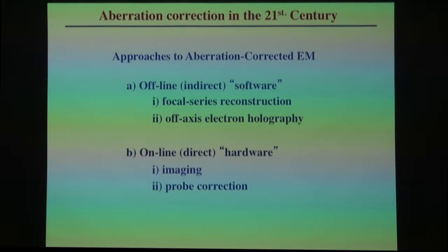because people are a bit worried about what high voltage microscopes do to a sample. You're going to cause radiation damage. These 1 million volt microscopes are very expensive. So maybe if we can overcome spherical aberration, then we can achieve better than 1 angstrom resolution at a lower voltage. Now, it turns out there are several different ways to correct aberrations. You can do it offline or indirectly using software. One approach is to take a focal series reconstruction. Another approach, originally proposed by Gabor way back when, is off-axis electron holography. The other alternative is to do hardware, so you have online or direct correction, and you can either do it with a corrector below the sample, which we call imaging correction, or with a corrector before the sample, which we call probe correction.